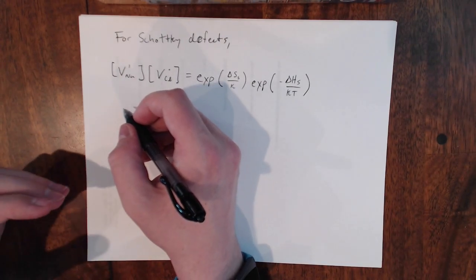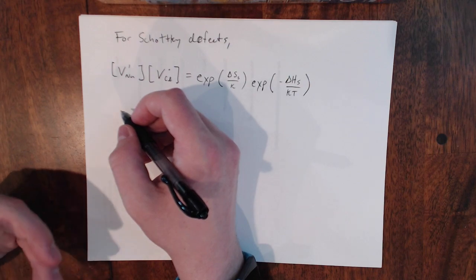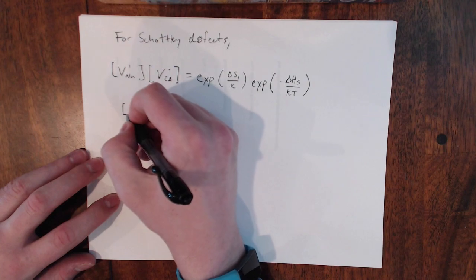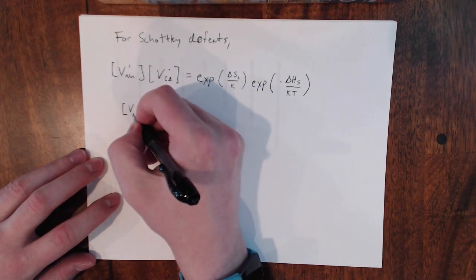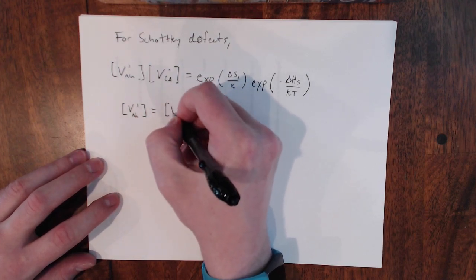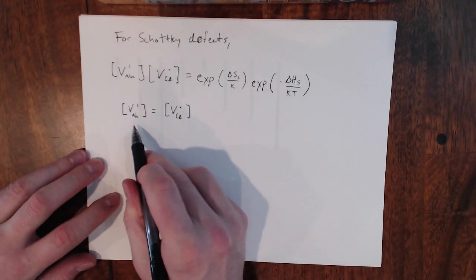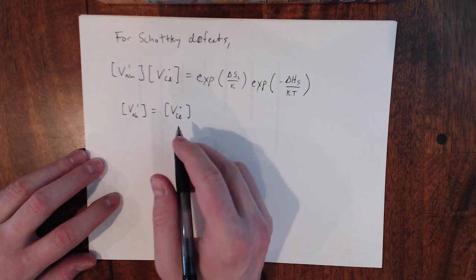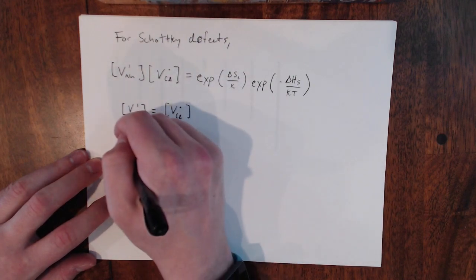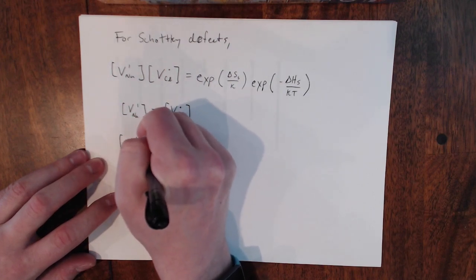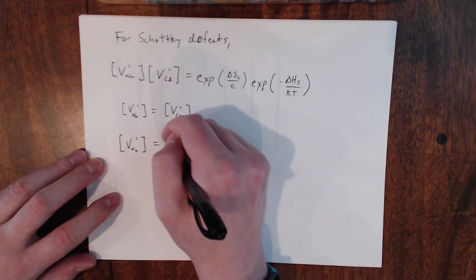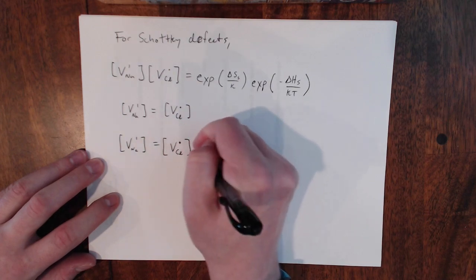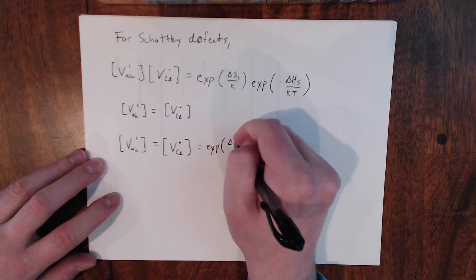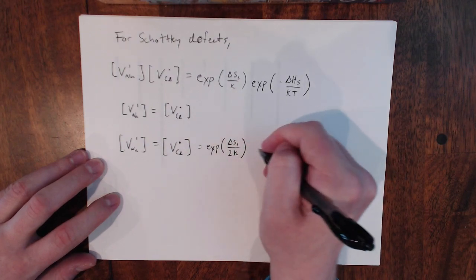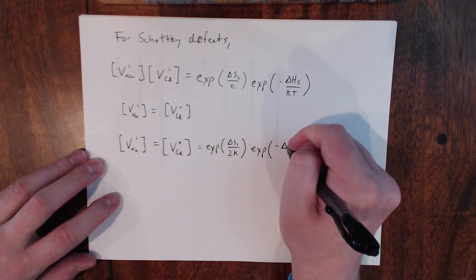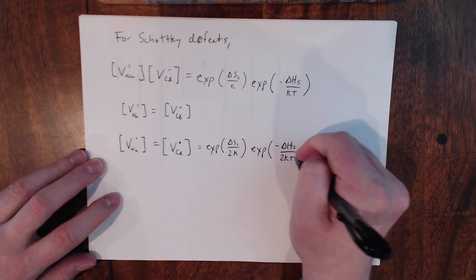If we're looking at these Brouwer approximations, and we think back to this reaction dominating, and nothing else is really accounting for these site ratios, then we can say that our vacancies are going to be equal to each other, right? So we can add in this expression that we have the site fraction of one is equal to the site fraction of the other. And so that simplifies our expression by a factor of two. And so we can rewrite that our sodium vacancy site ratio is equal to this same thing for chlorine. And that is equal to the exponential, but in this case, you'll see over 2kT. So we've added this expression here, 2kT.